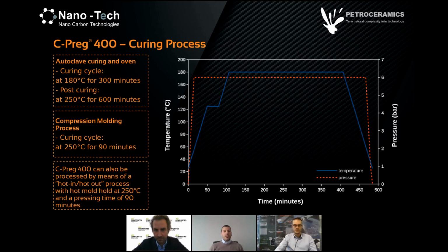It also has the possibility to be cured in a hot-in, hot-out process. So you can take the mold hot at 250 degrees, and you can put your laminate of Cpreg up and press it for 90 minutes. And get it out and put another one inside without letting the mold cool down. So as you can see, the Cpreg is quite easy to use and flexible, and the process flexibility allows everybody that has an autoclave or a press to use it. Okay, thanks, Andrea.